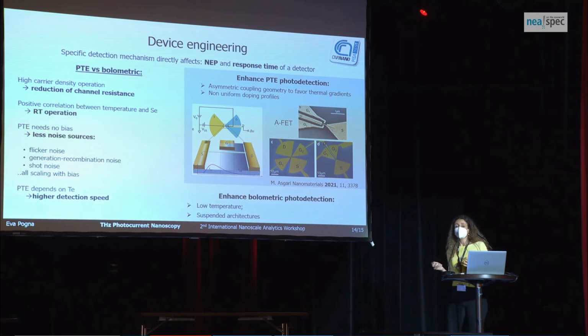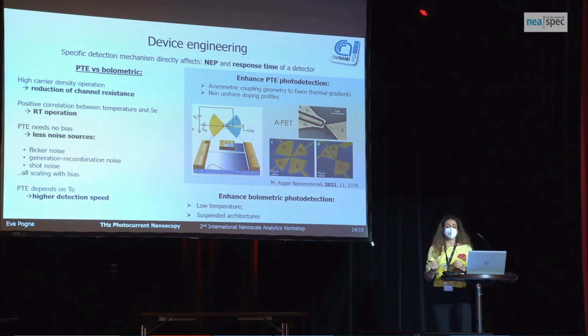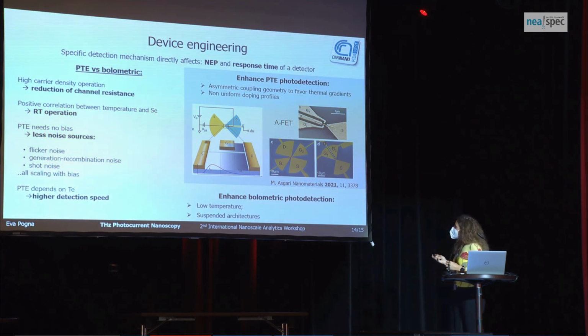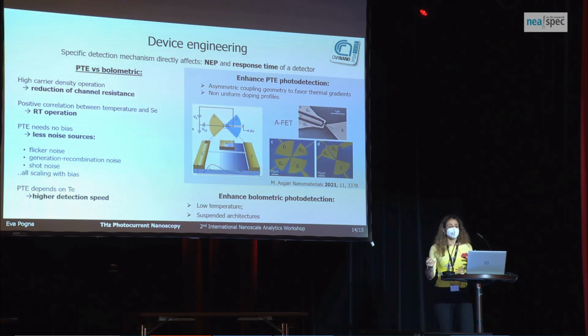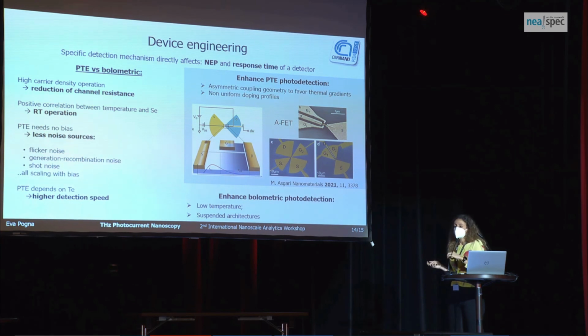In order to exploit the message that we have obtained from our near-field study, we optimized the device architecture by coupling the nanowire with a asymmetric antenna, which is favoring the gradient in the electronic temperature and enhances the photothermoelectric response. Another possible strategy that we are exploring is to have a non-uniform doping profile along the nanowire, or using twisted structures. And I would like also to say that bolometric effects can be an advantage if you have to work at low temperature, and it can be enhanced by using suspended architectures that quench the processes that release the lattice heat to the environment.